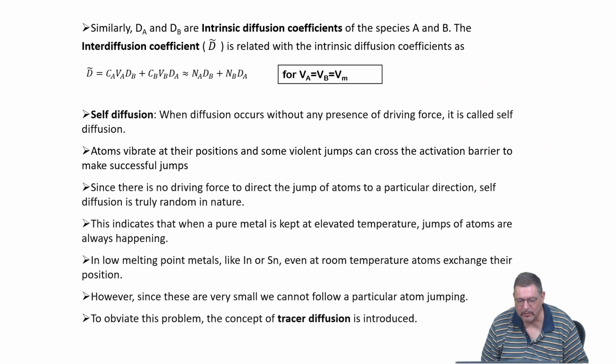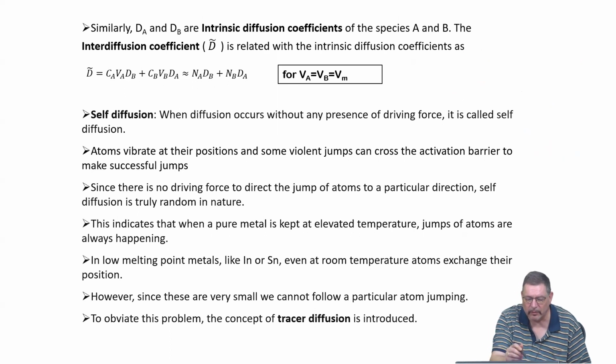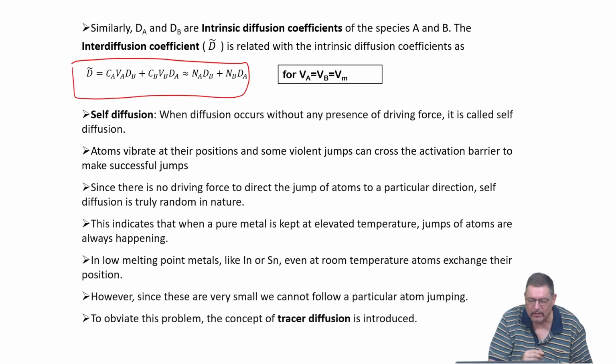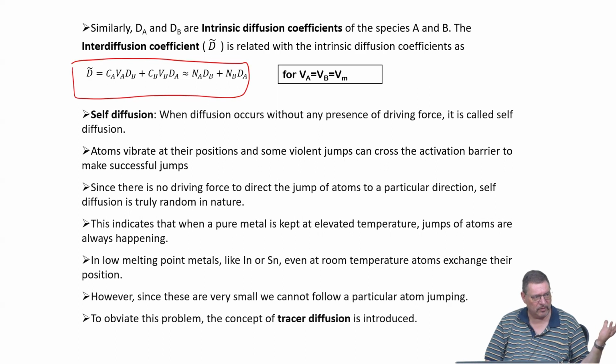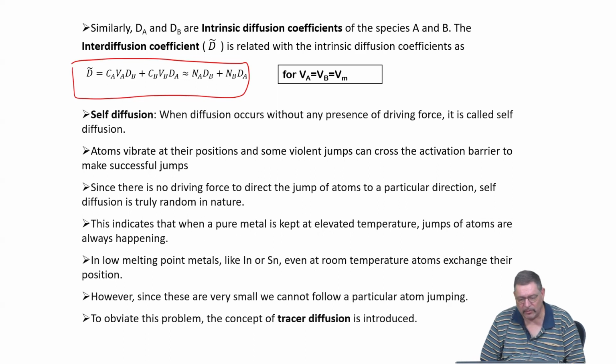Then obviously the diffusion coefficients also have these names, and the interdiffusion coefficient can be easily calculated based on the intrinsic diffusion coefficient. Intrinsic is without this tilde over the D, if the specific volumes of the two materials are rather equal. If they are very different, then one has to apply a correction term.